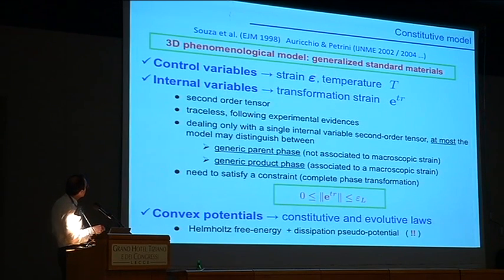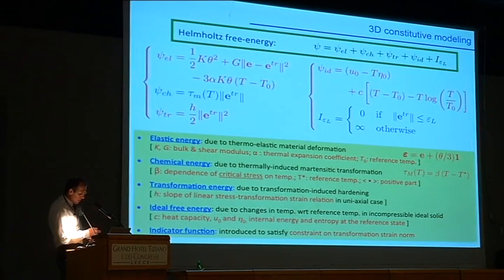So once you agree to work with this very simple set of variables, the model is proposed starting from the Helmholtz free energy, which is composed of a bunch of terms. In red, I reproduce the terms which are very classical, so I will not point your attention to the red terms, but I will point your attention to the blue terms, which are, at least for some community, more interesting. The first blue term is this one. This is the chemical energy. It is a quantity which should reproduce the effect of the martensitic transformation. In particular, this term is interesting because it's linear in the norm of the internal variable, which is kind of unusual in some standard plasticity models.